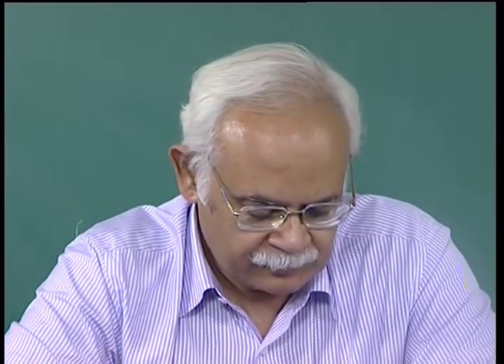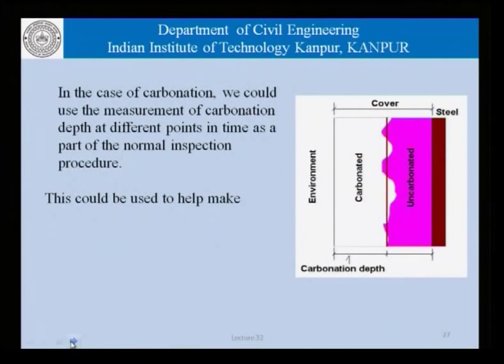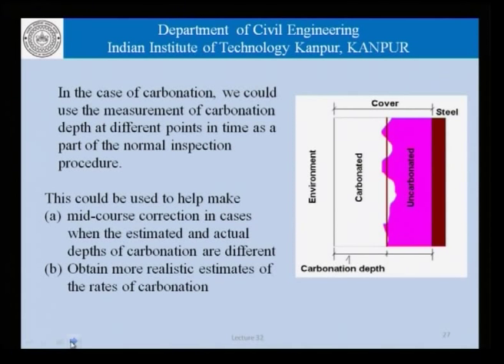Then as part of the inspection protocol, we could measure the depth of carbonation that has occurred at that point in time. What that will do is to help us make a mid course correction in cases when the estimated and actual depths of carbonation are different, and also obtain more realistic estimates of the rates of carbonation.